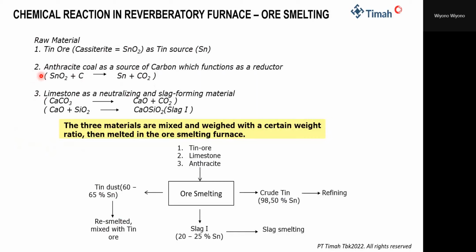Here, firstly the coal will oxidize to form CO2, and then CO2 will react with carbon to make carbon monoxide to reduce SnO2 to become Sn plus CO2. And then the limestone is a neutralizing and slag forming material, through the decomposition reaction. There are three main materials that we smelt in the smelting furnace.